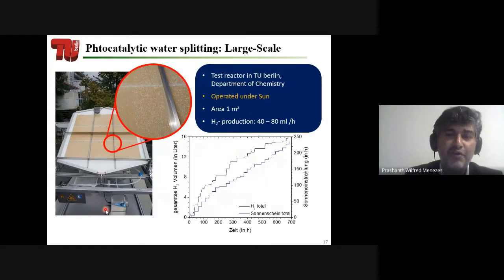I couldn't show you the video, I'm sorry, but what I can show you is the large scale setup we have built at TU Berlin. This is a large scale setup with an area of 1 square meter. We kept this area because we wanted to produce a lot of hydrogen. This instrument is on the roof of TU Berlin, and this is a test reactor. We wanted to show the public that we can really produce hydrogen just using sunlight. As you see, we took the same carbon nitride on some plates, and we shine light, in our case sunlight, and the bubbles here are the hydrogen evolution.